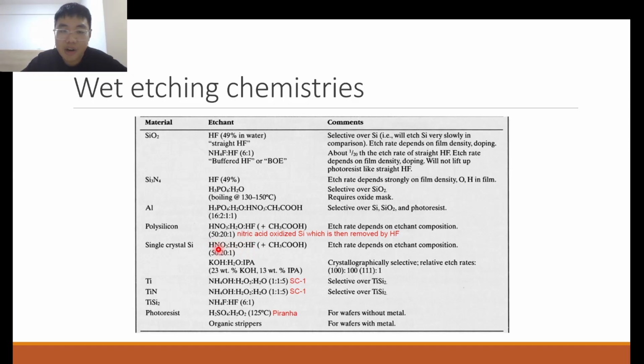So if we use this combination of reagents, nitric acid in water and HF, this etch is not considered crystallographically selective. It's not considered anisotropic, where it selects for certain planes faster than others. Why? Because this combination of reagents doesn't directly etch silicon. The nitric acid actually oxidizes silicon, and that silicon dioxide, which is an amorphous material with no clear crystal planes, is then dissolved by HF. So this is much less dependent on the crystallographic orientation of your silicon.